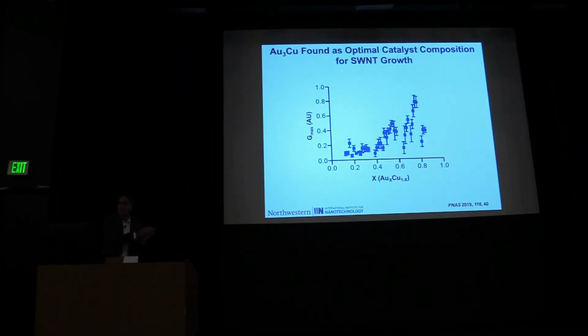Both in this case and the previous case with the HER, we then go back and we then synthesize them via the long and hard routes. But the point is we know which ones are worth making after we go through this particular process. And we try to confirm or not that the materials made by bulk solution synthesis mimic the properties of what we found in these types of systems.